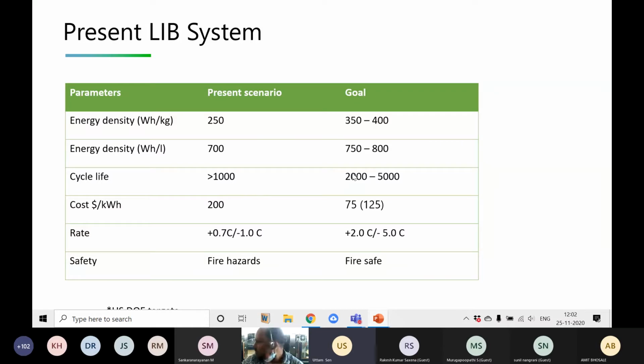It should be 1000 to 2000, mostly for NMC cells. The cost currently is slightly less than $200 per kilowatt hour. But the target is $75 per kilowatt hour at the cell level and $125 per kilowatt hour at the pack level. It should charge at a faster rate. Currently, we can charge at 0.7 C and discharge at 1 C. The target is to charge at 2 C and discharge at 5 C.